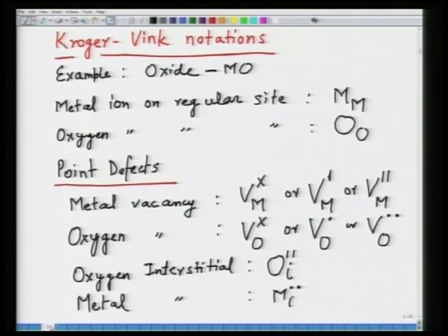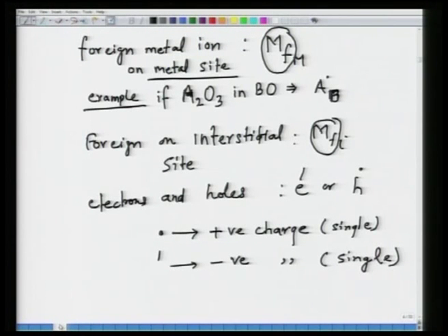And then we introduced the Kroger-Vink notations where each defect, whether charged or uncharged, has a particular notation by which it is denoted. In a nutshell, if a defect is positively charged, then it is denoted by a dot on top of it. So for example, in case of oxygen vacancy, you write it VO double dot if it is completely ionized, and in this course we will assume that all the defects are completely ionized. And if it is a negatively charged defect such as metal vacancy, then it would have a dash. One dash would mean single charge and two dashes would mean double charge, and so on and so forth.